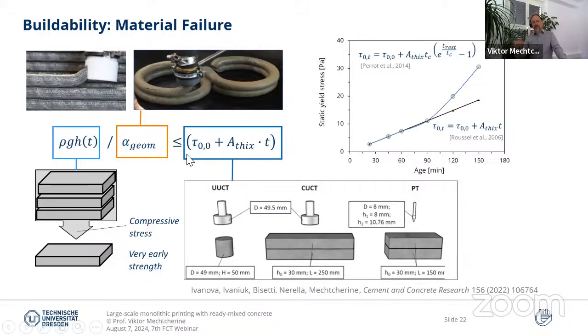And of course, in time, the resistance of the material will increase. So we know this concrete changes its rheological properties in time. We call it thixotropic behavior. And what you see here is an extension of this term by a thixotropy constant. And again, we have time here. So we can measure this development using different devices. Basically, what we want to gain is this relationship between the static yield stress, which is shown here, and the age of the material after the deposition. And in the first hour or 1.5 hours, it's mostly a linear relationship, which is of course good. But then due to hydration, it becomes non-linear in most cases, strongly non-linear, and then we need to use a non-linear relationship if we go that far.